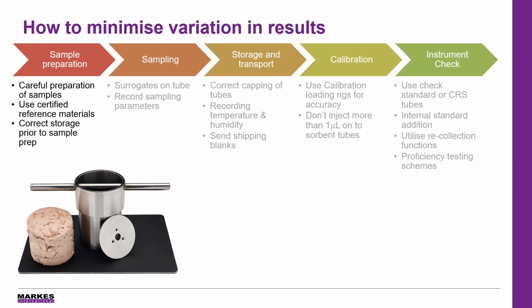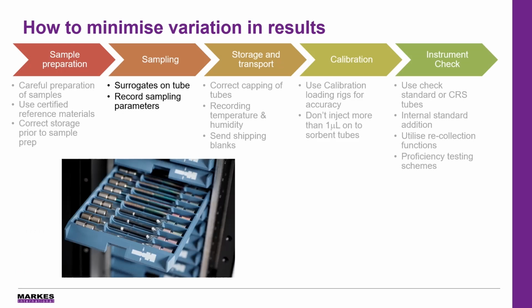The use of certified reference materials is something that many using chambers of all sizes would like to have. A material that emits a known concentration. Again, if you're interested in this, let us know and we can help point you in the right direction. Injecting the clean sample tube with a surrogate, such as deuterated toluene, prior to sampling from a chamber or any other environment really, can be used to identify if there are any issues when sampling.